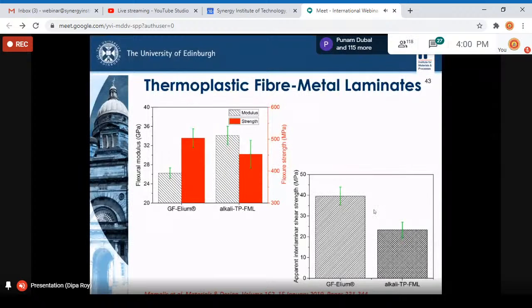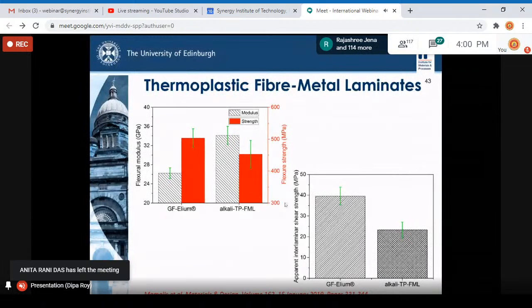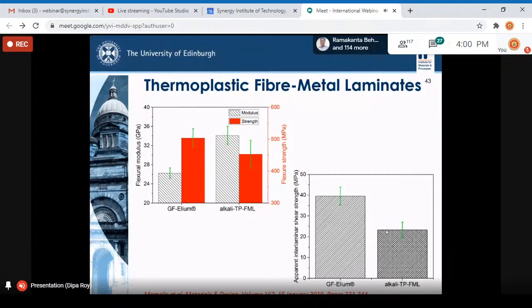So in case of a purely glass fiber acrylic composite, this is a homogeneous system. It has only the glass fiber and the acrylic resin. So in that way, it's a homogeneous system, and this can have a very good interfacial bonding, whereas in case of fiber metal laminate, it's a very heterogeneous system. It has composite and it has metal, so there are dissimilar materials. The joining of dissimilar materials is always a weak point. That's why we wanted to make this bonding as strong as possible, so that we can have these hybrid materials performing well under different loading conditions.